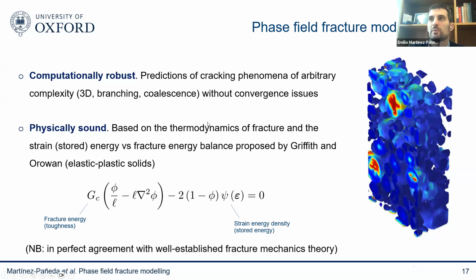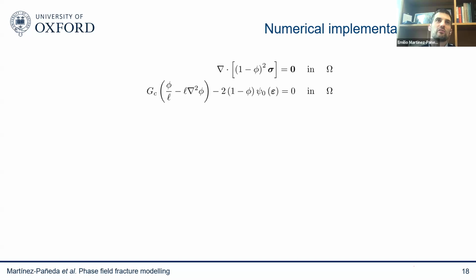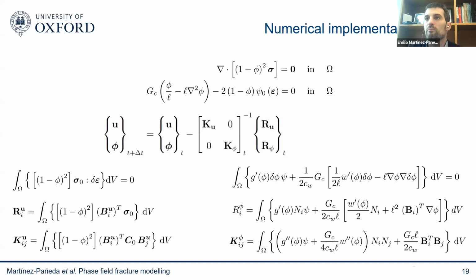But let me tell you a little bit about these two aspects. Why is it computationally robust and why is it physically sound? So let's look at the numerical implementation first. So those were the strong form equations that I told you before. And of course, if you want to postulate the weak form, then basically you have this for the mechanical problem and this equation for the phase field problem. And you can see that you're basically solving this kind of coupled problem where you solve for the displacements and the phase field. You define this stiffness matrix that is the same as usual, just with the phase field degrading the material capacity. And then you have the residuals, of course, for the displacement and a residual for the phase field and the stiffness matrix for the phase field.